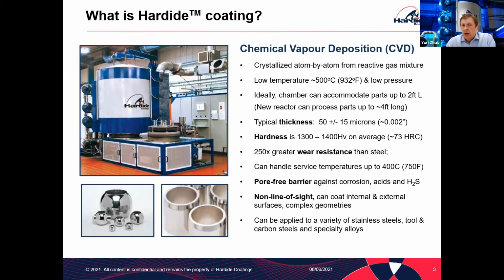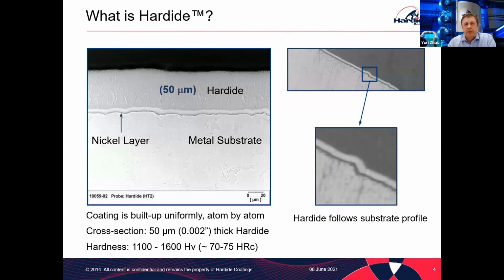As I mentioned, the coating is non-line of sight, so we can coat internal surfaces, external surfaces, complex shape parts, and we can coat a variety of steel components, stainless steel, tool steel, carbon steel, nickel-based alloys, copper-based alloys, so various metals. We coat metals mainly. What you see on this slide is a cross-section of a 50 micron thick coating. You can see that it essentially follows the substrate. It's a conformal coating. It will repeat the profile or the features of the substrate.